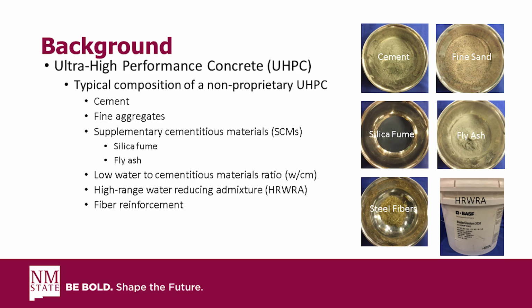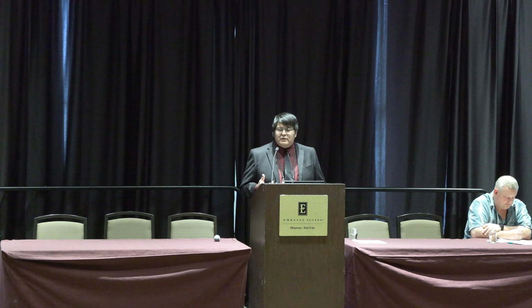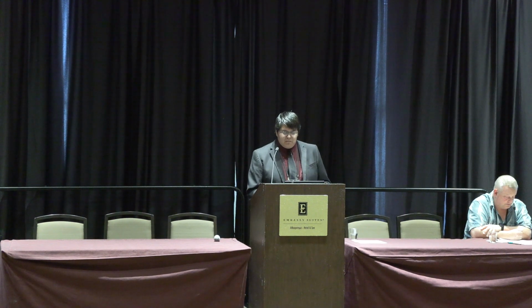And in order to have our ultra-high performance, we need our high strength steel fibers. In this case, we're using needle fibers that are 13 millimeters long and have a length to diameter ratio of 65. So it's a very fine material, or fine fibers.